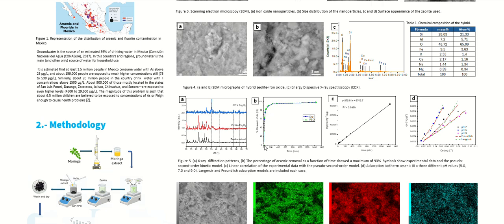Section B, the percentage of arsenic removal as a function of time showed a maximum of 93%. Symbols show experimental data and the pseudo-second-order kinetic model. Section C, linear correlation of the experimental data with the pseudo-second-order model. Section D, adsorption isotherm of arsenic(III) at 3 different pH values of 5, 7, and 9. Langmuir and Freundlich adsorption models are included in each case.